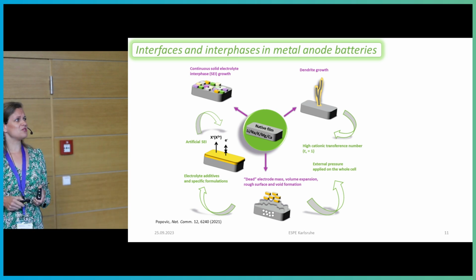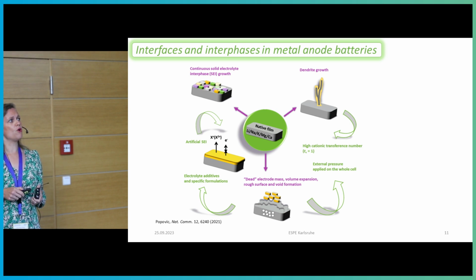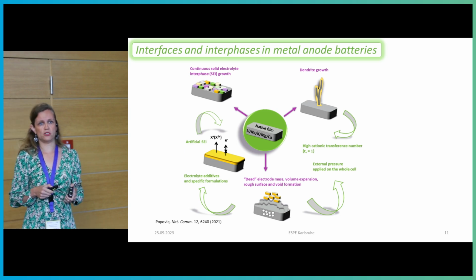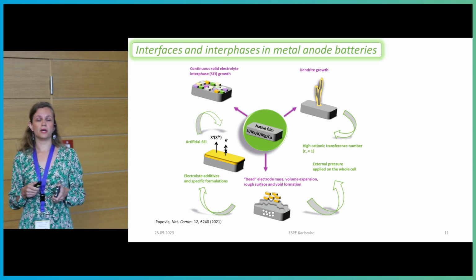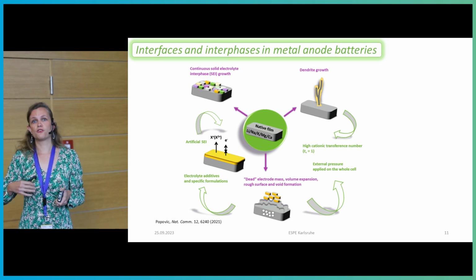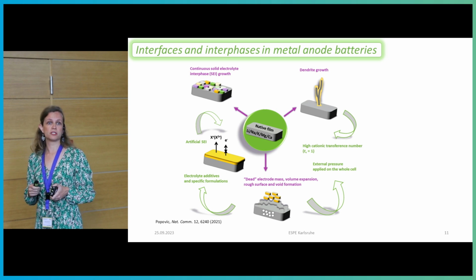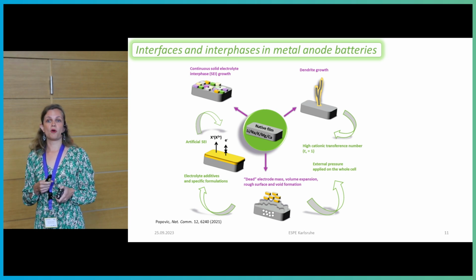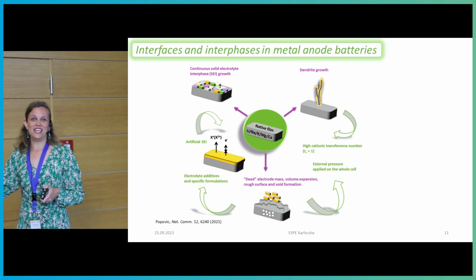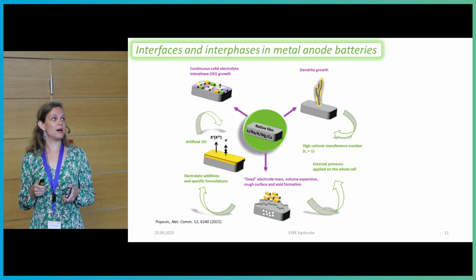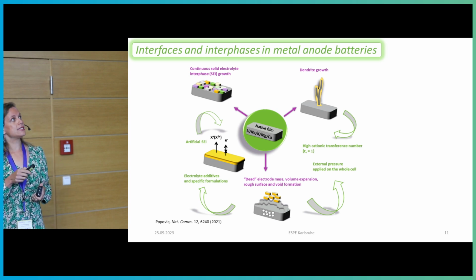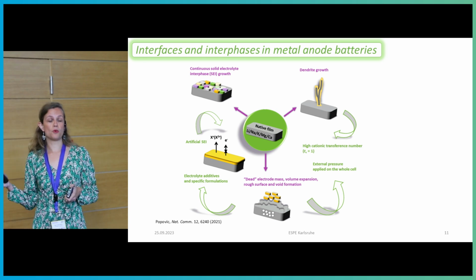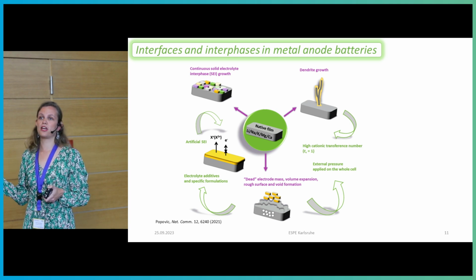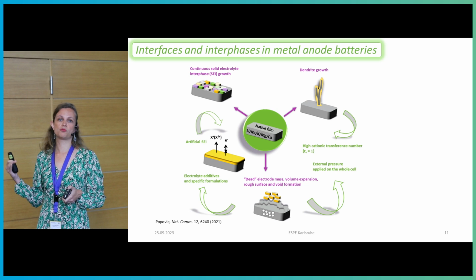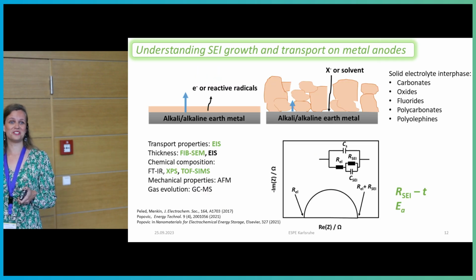And then I would like to stress that we have additional problems, and these are all of these dead electrode mass, volume expansion, rough surfaces, and void formation. These are not actually solvable. And I think this is the reason why people are trying to go towards these anode-less materials, because in those, these kind of problems occur at a later stage in the kinetics of the materials. But in my opinion, if we think about anode-less, the continuous SEI growth will always be a problem, because we are always depositing fresh lithium or fresh sodium and fresh potassium, and these are really, really reactive materials.